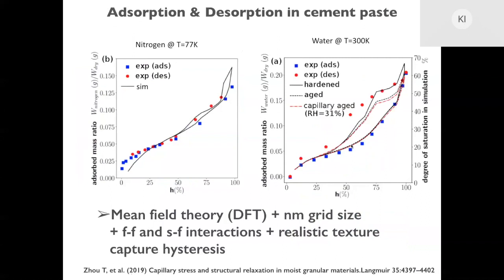So basically, as long as we have the right interactions from atomistic scale, and also we have the right grid size, that should be very small, because we need to have the fluid, which is water-based, so water molecule 3 angstrom, and we need to have a realistic pore network for cement, so we need to go up to half a micron in order to have the full pore size distribution. Of course, the simulations were very heavy because of this reason, but they're doable due to parallelization.